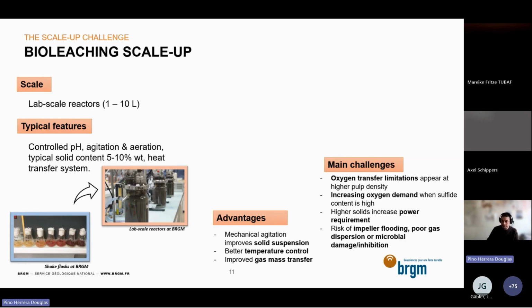But we still have some problems. When we increase the solid content, we increase the oxygen demand, particularly when the sulfide content is high. And then we may have an increase in power requirements. When we try to fulfill this in the small reactors, we rapidly encounter risks of flooding the impeller, poor gas dispersion, or microbial damage and inhibition because of the high velocities we need.